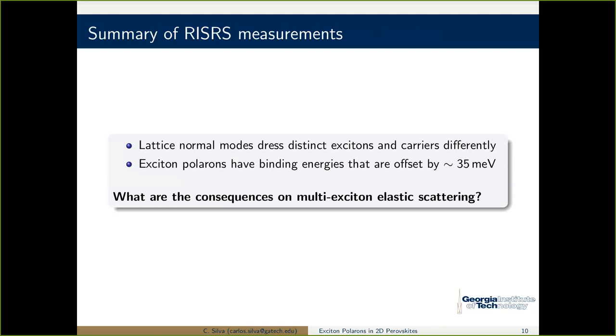But let's also ask ourselves, what are the consequences now on dynamics? I will not show you some work, because of time, that was also published last year in Chemistry of Materials. It shows that when you inject photocarriers, let's think about an LED. If we want to make an LED of these materials, you're going to inject photocarriers. They're going to recombine. What are the timescales? How does the fact that different phonons couple to different excitons differently govern the dynamics of charge recombination? And they do.